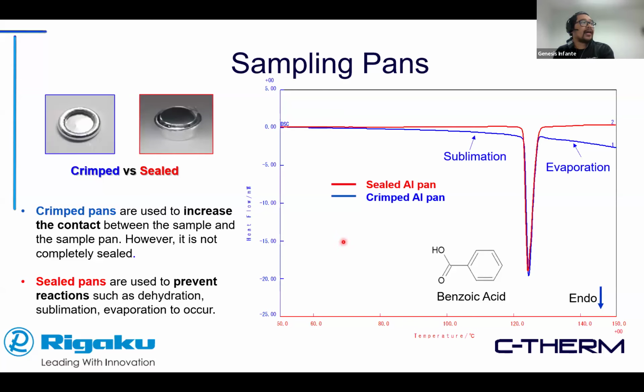Another important factor to consider is something like crimping versus sealing. Different applications might need you to insulate or isolate your sample during the test itself. So let's say if you have evaporation or some sort of phase change, you might want to make sure that there's no significant change in your sample during the test. Crimping is by definition used to increase the contact between the sample and the pan, but keep in mind that this doesn't mean that it is sealed against high pressure conditions. So if you want to make sure that your sample is actually touching the bottom of the surface, which is what you need in general, you want the contact between the sample and the pan to be maximized as much as possible.